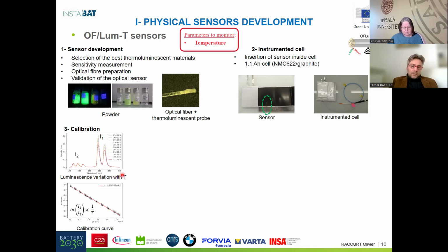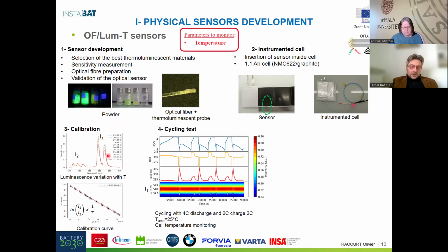It's a good opportunity for me to explain how it works. The signal from the sensor comes from the optical material and gives two peaks in the spectrum. One peak remains constant with the temperature, and the second one decreases with the temperature. And by monitoring the ratio between the two intensities, we have a linear relation between the logarithm of this ratio and the inverse of temperature. And by measuring the luminescence signal, we can monitor the temperature inside the cell.